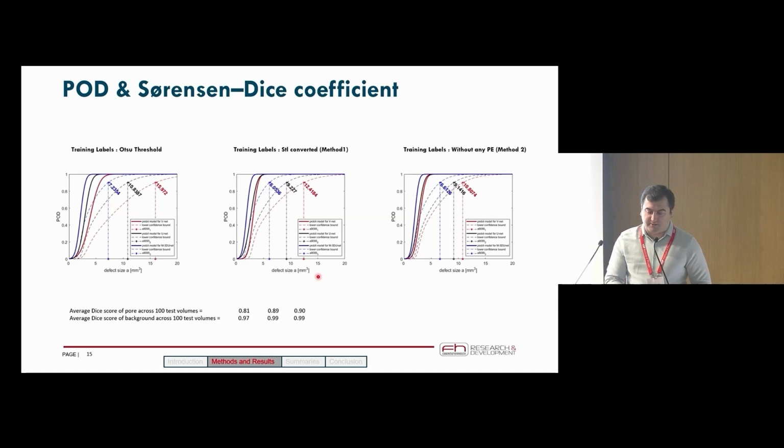With both methods, we achieved an increase in the minimum detectable region through the creation of accurate ground truth. But there is still potential to increase this detectable region because we only used specific or known geometries for the training data. We haven't used any complex shapes in the training data. If we also add these complex shapes, then we can still increase the detection.